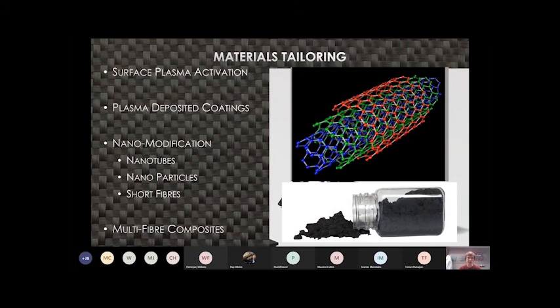So in other words, here what you can do is add various nanoparticles, such as carbon nanotubes. There would also be core shell rubber, which is a very popular one, as well as various short fibers. An example here on the right hand side is a carbon nanotube, and this is what the powder looks like essentially when it's bought. By adding these in, carbon nanotubes in particular will increase stiffness values for the matrix materials. Other particles such as the core shell rubber will increase the toughness of materials, but could decrease their stiffness. So by combining these different powders in different quantities, you can actually raise or lower various mechanical properties till you get to the point that you actually want in your final product. So that's very, very useful in this sector.